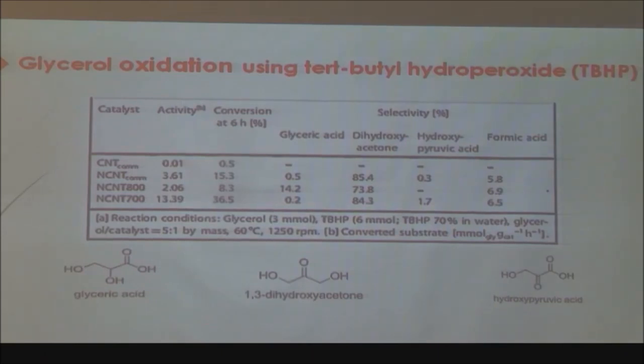And when we analyze the different products by GC analysis, we come to know that this is the one which is being made in highest amount. If you see this is NCNT, the selectivity here is very high, but the conversion is less. So this material, where we are able to get 36%, again you see this is not a very high conversion, but because we did this reaction for the first time, this went for a very good publication, because we demonstrated this process for the first time, that too metal free. So that was the beauty of the work, that even though the conversion was low, it ended up in a very good journal for publication.